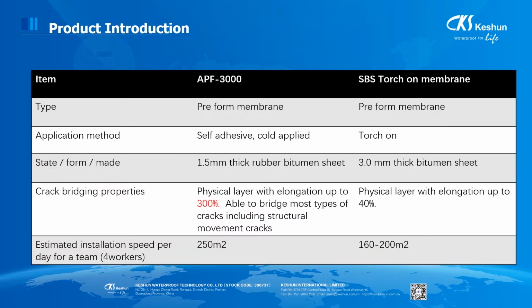Okay, then let us compare APF-3000 and SBS torch membrane. Both are pre-form membranes, but APF-3000 is self-adhesive membrane, and SBS membrane needs to use torch to apply. As we all know, the common SBS torch membrane is bitumen on polyester. The membrane needs to be at least 3 mm to make sure when you torch the membrane, fire will not destroy the polyester. And for APF-3000, we don't need to make it that thick to protect the film from fire damage. Due to these reasons, we can save half of our transport cost. I think most of our clients import the material by container, so this thickness really matters a lot.